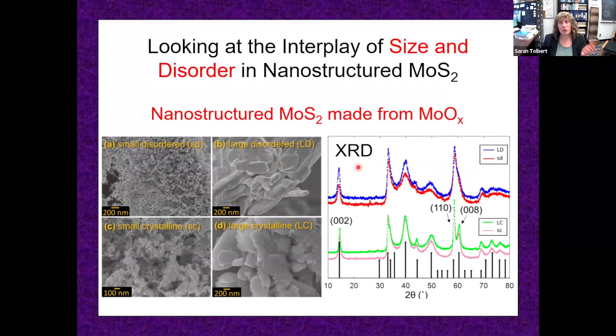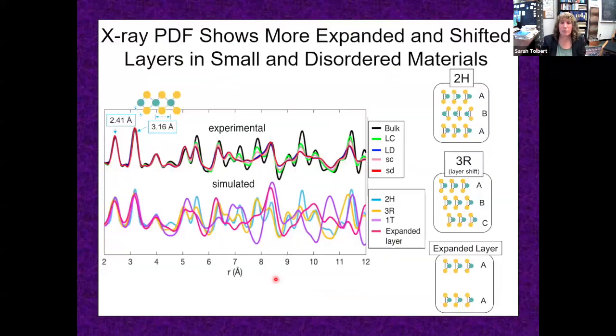And this is X-ray diffraction. It's, again, that probe of structure. And what we see is that our diffraction peaks are very broad when we do it at low temperature. That means it's a disordered phase. When we do it at high temperature, our diffraction peaks are very narrow. So we can now make a grid of small, disordered, small, ordered, large, disordered, and large, ordered, and look at how that controls the ability to charge quickly.